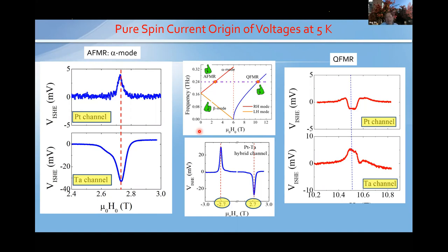So essentially, in our paper, in the supplemental part, we actually directly detect the temperature rise using resistive thermometry, essentially using the platinum and the tantalum itself. In the case of the platinum, we see the resistance rise at the resonance, which has exactly the same shape as the inverse spin Hall voltage resonance. And in the case of tantalum, because it has a different slope, the resistance actually decreases, but it has the same line shape as the resonance, like a Lorentzian line shape.